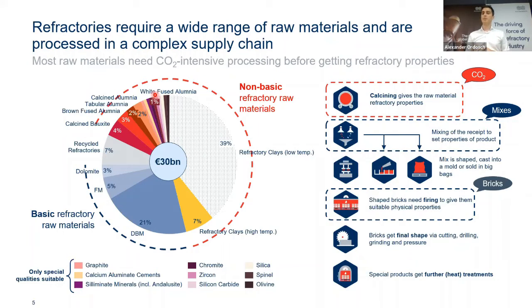And this processing step is normally quite CO2 intensive, because the processing steps normally include calcining of the material, so basically heat treatment. For example, you take the magnesite, so magnesium carbonate, and you put it into a rotary kiln to basically get rid of the CO2 to arrive at MgO, so periclase. And this periclase, this mineral, has a very high melting point of about 2800 degrees. And this then is the foundation for the refractory properties of the magnesite-based products that we sell very prominently.